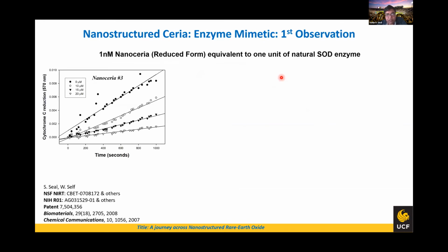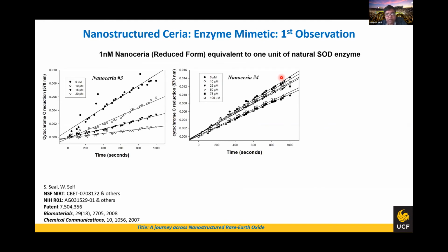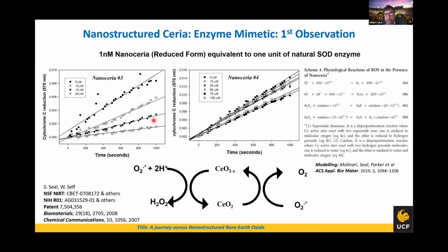So we have a series of work that we did with Dr. Sell. We created two different materials, cerium 3 and cerium 4, with more plus 3 and plus 4 states. And you can start to see as this curve goes down, that means these are more reactive. This material with more plus 4 state is also somewhat active, but not as active as this material. So over time, we postulated the reactions. The cerium 3 on the nanostructure really interacts with the O2 radical. This is mostly a disproportionation reaction. And then it is catalyzed to H2O2, and then the catalase takes over and degrades it to H2O and O2, and the overall reaction gets regenerated over and over again.